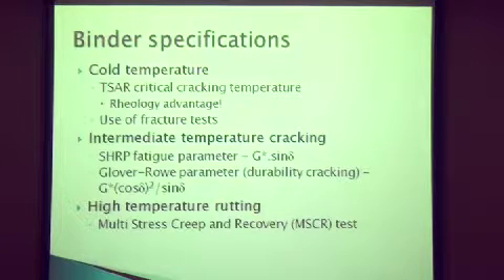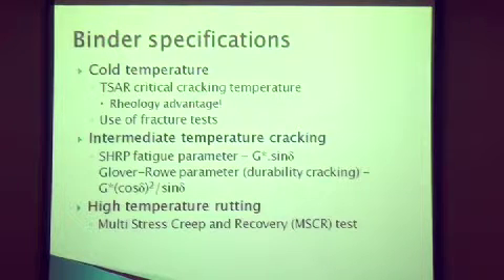In the cold temperature cracking, what we have is a piece of software that we developed called TSAR, which does a critical cracking temperature analysis. And what this piece of software does is it really shows the importance of rheology in trying to look at the performance of the asphalt binder, and it does make use of fracture tests. So it combines the use of a fracture test with the rheology coming out of a bending beam rheometer.